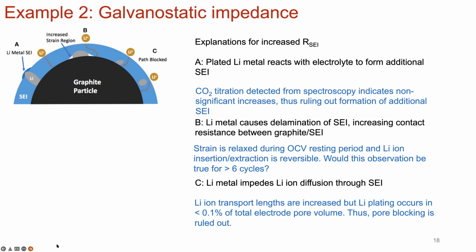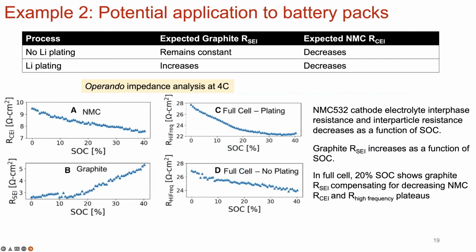So the impedance data is really pointing towards the fact that there's potential delamination, but it's partial, and the strain over time actually can be relaxed if you have just a resting period right after.